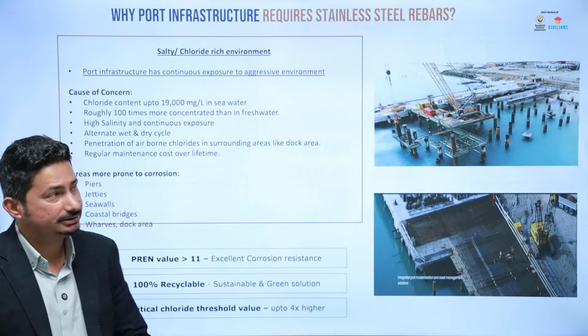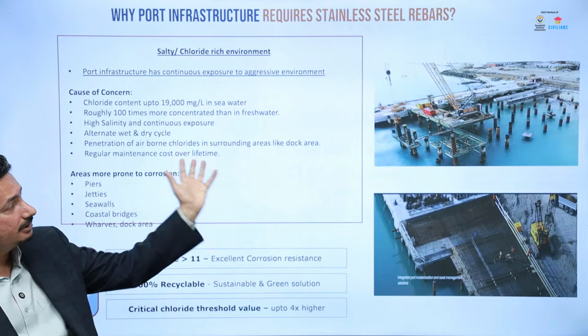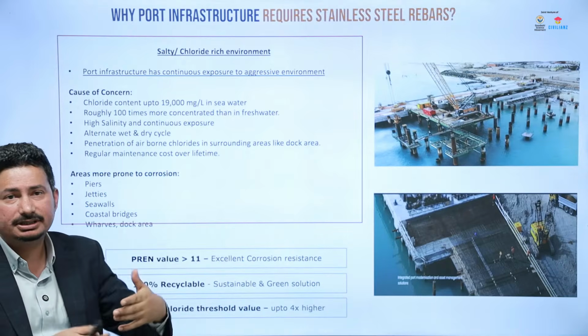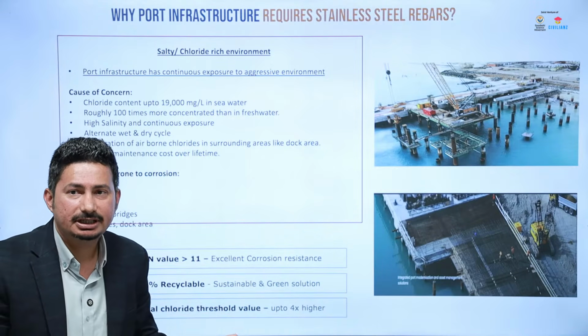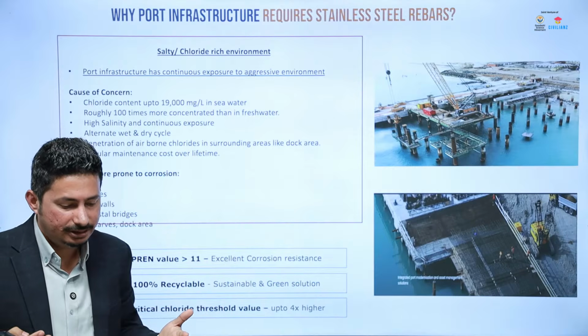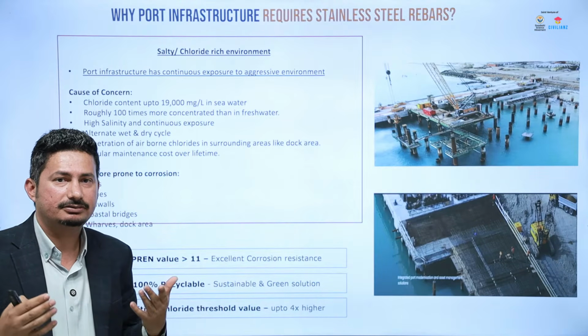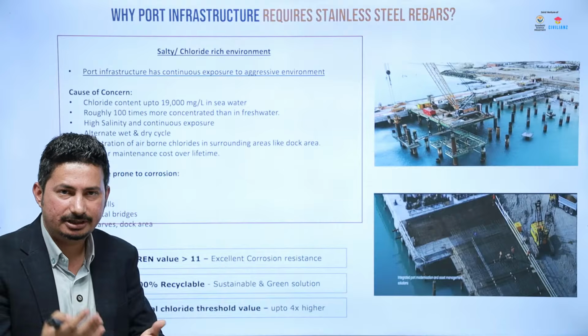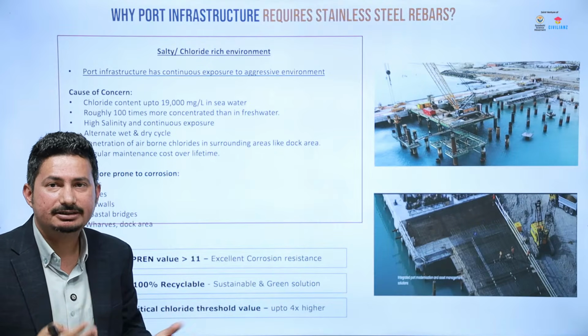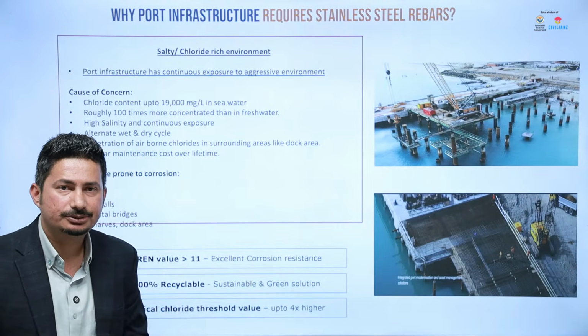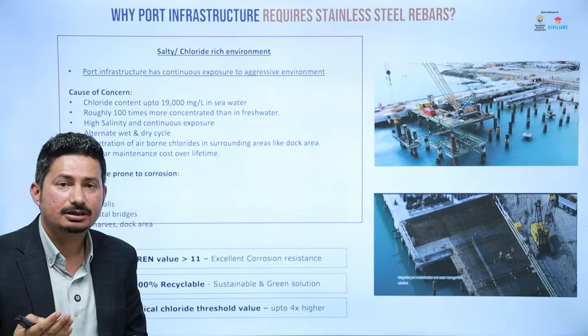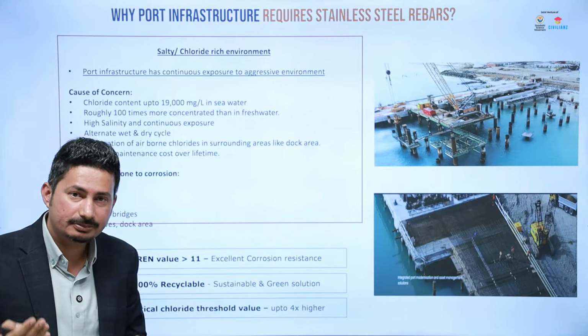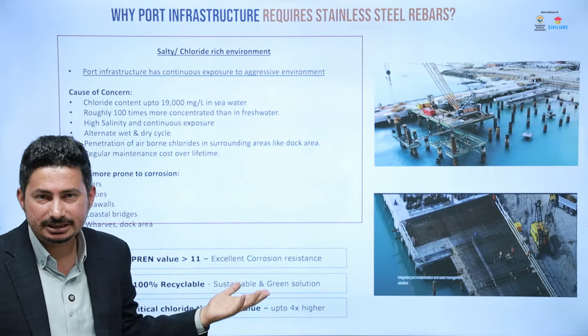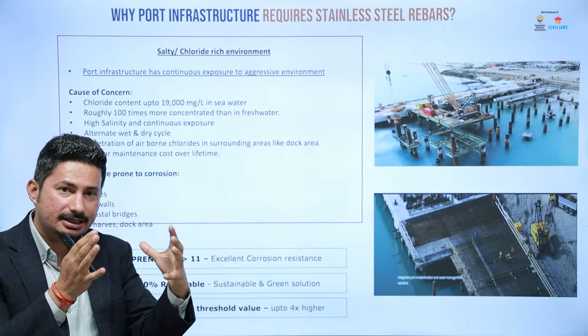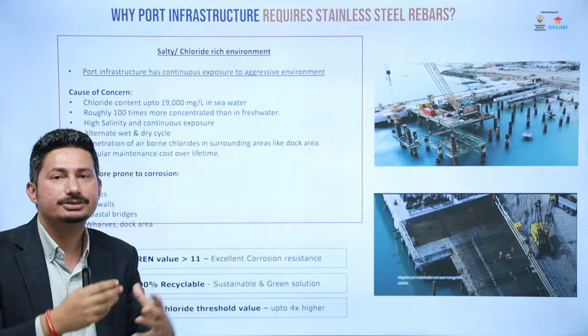Then talking about some of the applications. The first application is port structures. Port structures, as we all know, are highly exposed to the marine environment, and in the marine environment, chloride-induced corrosion is very prevalent. Therefore, using stainless steel rebar makes a lot of sense. The PREN value, the pitting resistance equivalent number, of these rebars is much higher compared to CRS or TMT rebars, as we discussed in the previous slides. So the structures will last longer if you are using stainless steel rebars.